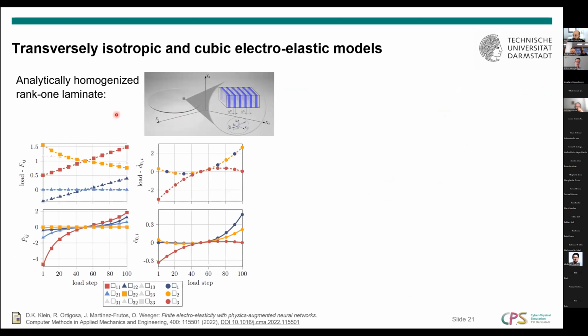So basically, we applied this now also to an analytically homogenized rank 1 laminate, where we have 2 layers of materials with different material behaviors, which result in a transversely isotropic overall behavior. So we take the transversely isotropic invariants, generate some data, fit the model, and here you see a visualization of some test cases where this would be the applied deformation gradient and the resulting stresses, and the applied electric displacement field and the resulting electric field, where again the data would be the dots and the continuous lines would be the model prediction, and we get a very good accuracy here for this physics enhanced neural network model.